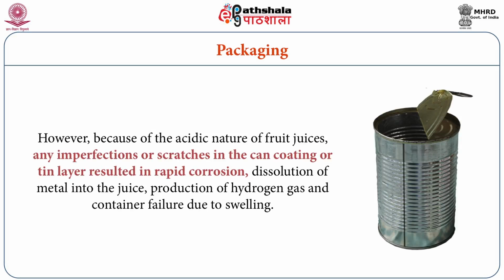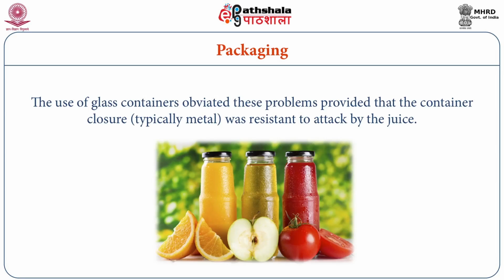However, because of the acidic nature of the fruit juices, any imperfections or scratches in the can coating or tin layer resulted in rapid corrosion and dissolution of metal into the juice and production of hydrogen gas and container failure due to swelling. The use of glass containers obviated these problems. Care should be taken with glass bottles during hot filling to avoid breakage of glass.